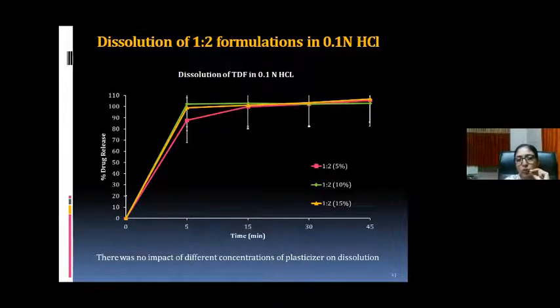Now, dissolution studies were carried out for the 1:2 ratio in 0.1 normal HCl. Here you can observe that after 15 minutes there is no impact on the drug release. That is, different concentrations of the plasticizer have no impact on the dissolution. It remains nearly the same.